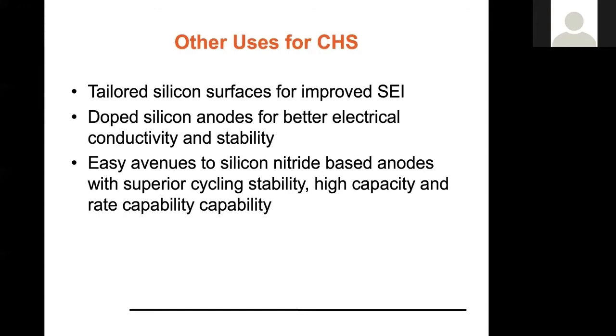CHS can be readily doped with a wide variety of commercially available materials to give doped silicon anodes for improved stability and better electrical conductivity. And a material that's gaining a lot of interest right now is silicon nitride-based anodes, and CHS offers pathways to make those materials in a very similar way. And those materials have shown to have a very good cycling stability, high capacity, and very good rate capability.